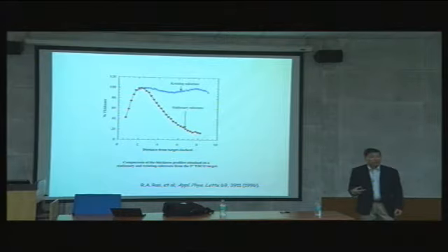Actually with a 3-inch diameter target, you can get an 8-inch wafer area uniformly covered within plus minus whatever, 5-10% region. Okay, so that is very attractive. Other techniques are much harder to adapt to this, but with this one you simply have a simple rotation, a spinning target, and those things. And there's a composition measurement, and the yttrium-barium copper oxide composition is relatively uniform here. A lot of the composition measurements we do are wavelength dispersive X-ray spectroscopy measurements, and the error bar is relatively small, and that's what you get.